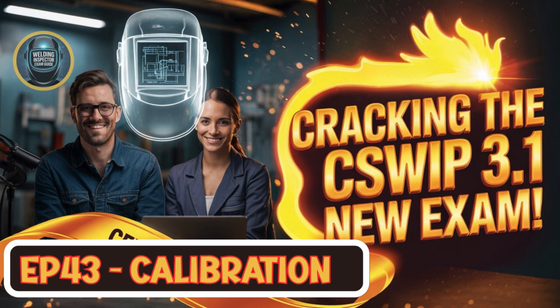Right. Let's talk accuracy levels then. We've mentioned standard and precision grades. What kind of tolerances are we actually aiming for? Does BS 7570 or BS EN ISO 17662 specify numbers? They do. For what they call grade 1, which is sort of general purpose equipment, the rule of thumb is generally plus or minus 10% for all parameters. Plus or minus 10% for standard. But for grade 2, which applies to automatic or automated equipment, our precision grade, effectively, the requirements get much tighter. Welding current should be within plus or minus 2.5%. Wow, 2.5%. Yeah. And other parameters, generally within plus or minus 5%.